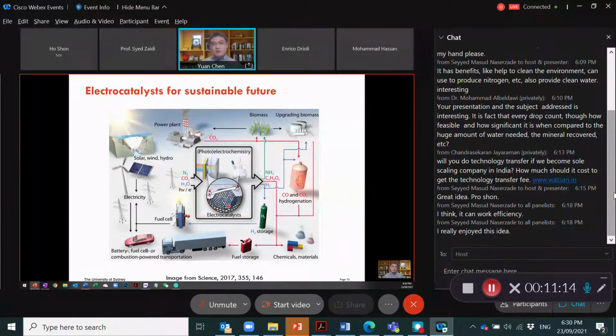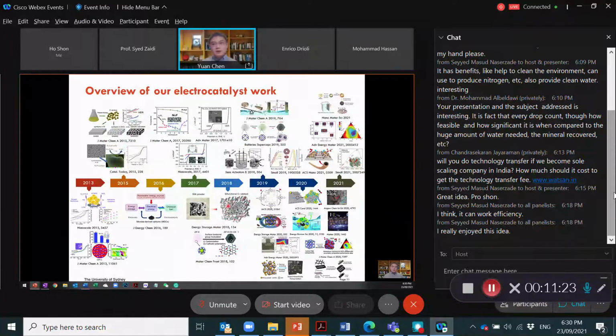While carbon material, especially carbon nanomaterial, is a very good potential candidate for those catalysts. On the one side, they have a large surface area and high conductivity. On the other side, if you dope different elements into the carbon, they actually become catalytically active, so they can serve as a catalyst. So we started this part of the work from 2013. Initially, we were looking at how to dope the graphene and the carbon nanotube with different components. And then we noticed that we can also use bio precursors, for example, bacterial cells or milk powder, and those can be used as a precursor to produce a very high activity catalyst.